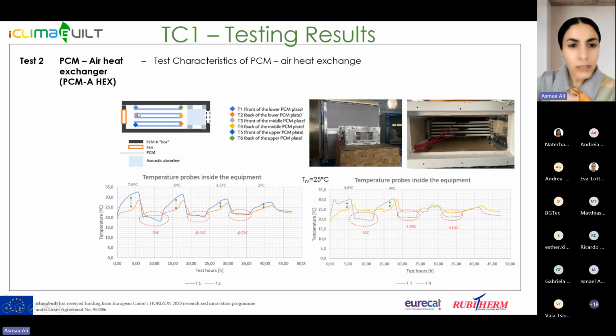Here these two sensors, from the beginning and the end of the plates, show a big difference. The air comes in at a high temperature, close to 35 for example, and ends at temperatures around the melting point of the PCM for a long time, and it has a shift in both temperature and time. As the temperature difference increases, the PCM can regulate the indoor more, and it can provide more consistent temperatures. These are temperatures of the lower and middle sensors of the plates as examples.